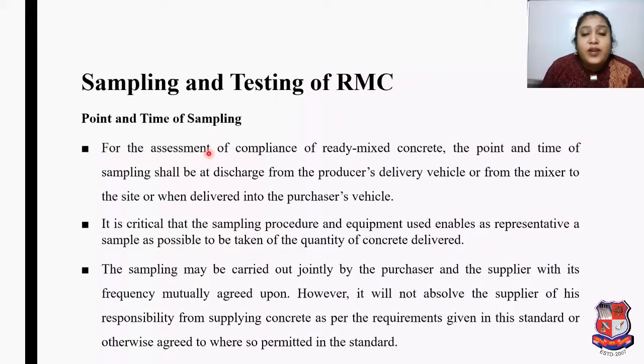For the assessment of compliance of ready-mix concrete, the point and time of sampling shall be at discharge from the producer's delivery vehicle or from the mixer to the site, or when delivered into the purchaser's vehicle. It is critical that the sampling procedure and equipment used enable as representative a sample as possible to be taken of the quantity of concrete delivered.